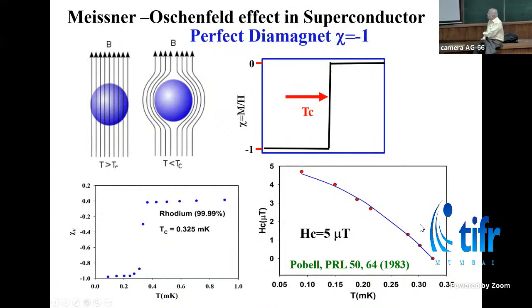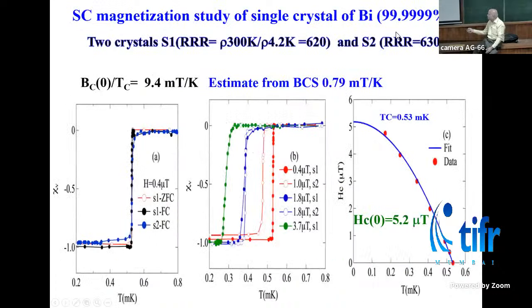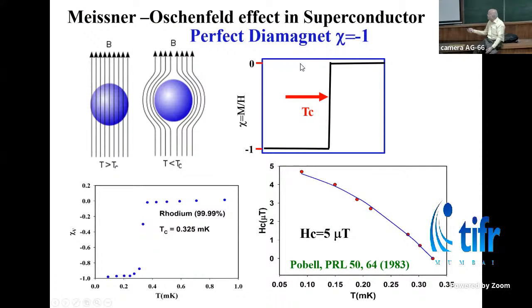Okay, so this is how you discover the superconductivity. A superconductor, when cooled below its critical temperature, expels the magnetic flux. So you can measure that expulsion by having a magnetometer. Since you developed a magnetometer, you must make sure that it works. So we took Pobel's sample, not his sample, it's our sample. That's why it's a little less than 350 microkelvin. His is very pure and so on. And so at least we see that our results match with the system, the magnetometer works.